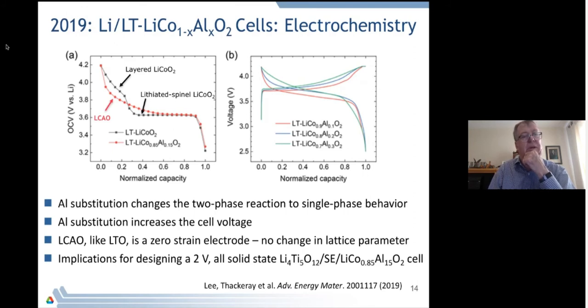If you look at the aluminium-substituted material in red, the aluminium substitution changes the nature of this reaction radically from two-phase behavior to what seems like an apparent single-phase process. Aluminium substitution also increases the cell voltage.